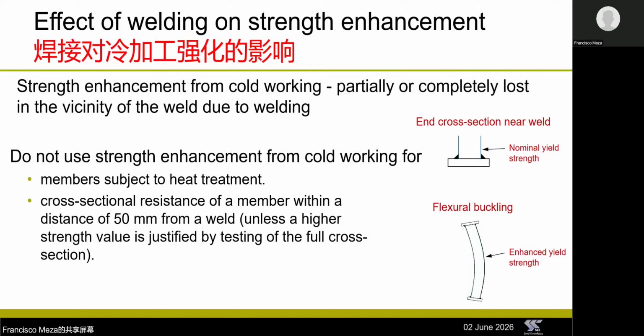Now, the type of welds I am referring to are welds that are carried out after the fabrication of the section. So this would include, for example, the weld that you might use when attaching an end plate to the column, but it doesn't include the seam weld that is used during the fabrication of the section, because the presence of this seam weld is already taken into account by the equations that are used to calculate the average yield strength.